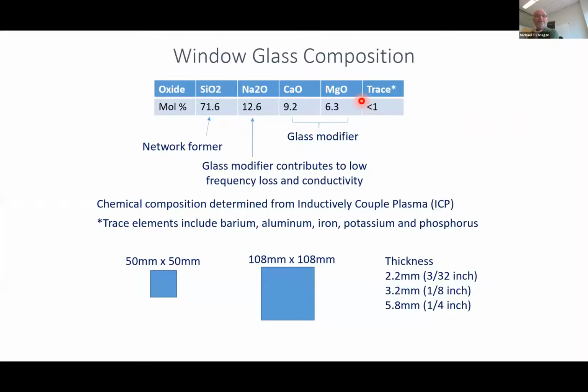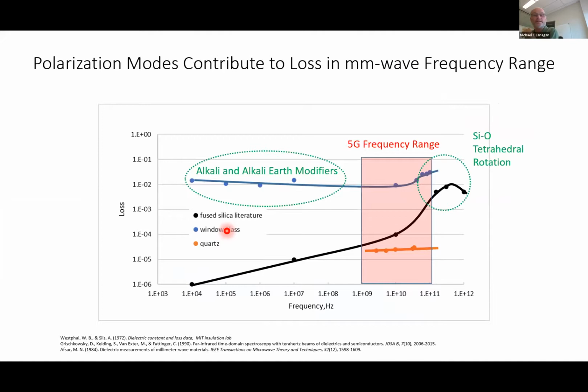So just window glass, if we move from pure silica to something that's window glass, it's still mainly silica, silicon oxide, but it has a lot of additives, modifiers like sodium oxide, calcium, and magnesium oxide. And so a typical window glass composition has this, as I said, mainly silica, but some other modifiers shown here. We actually just looked at window glass samples and were able to measure the dielectric properties over a broad frequency range. So in this case, I'm only going to show the loss, but here's the quartz shown here.